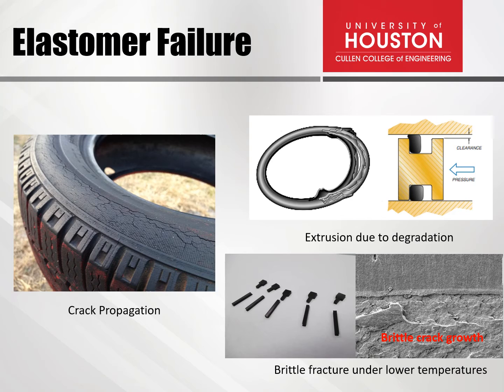In our daily life, after long-term service or shelf storage, you will notice failure caused by degradation of elastomers in tires, valves, or cooling systems. Such degradation may lead to crack initiation or accelerate crack propagation. Even without cracks, elastomer components may not function at their original pressure rating, which is extremely dangerous in some scenarios. For instance, failure of packing elements in a blowout preventer may result in disaster in oil and gas production.